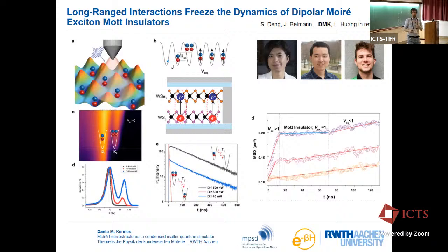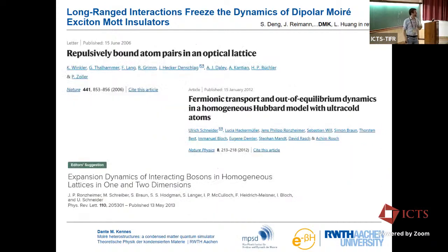Now, when they increase the density of excitons by just pushing the system harder, more laser power, you go to this regime up here. So you again see, I create the exciton cloud, it expands a bit. Sorry, this is size of the cloud in a sense, and this is time. Yeah? And then it freezes. Yeah? It's like just a regime where it seems to stop expanding. And then there's something setting in where I lose basically excitons. This is up here. Okay? So that's very, very strange, right?